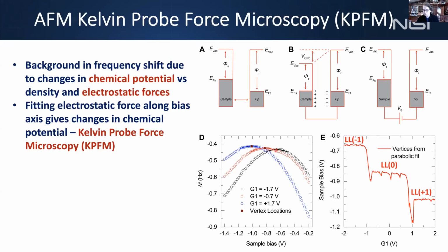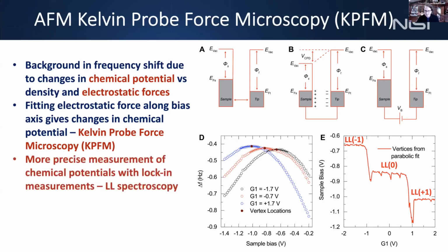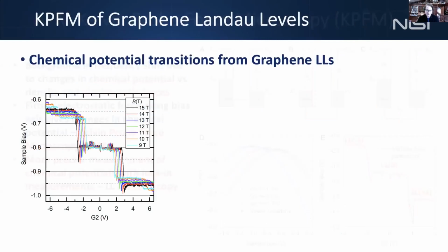And if I just measure that vertex as a function of gate voltage, I get this staircase. This is nothing more than the chemical potential changing due to the Landau level formation. And so we can read off directly the energies of the Landau levels, including the broken symmetry states. Now, this was done in a DC method where I just fit the vertex. You can do this much better if I do lock-in measurements and I modulate the bias a little bit and do a very sophisticated lock-in technique. Then you can do this chemical potential mapping with much more fidelity.